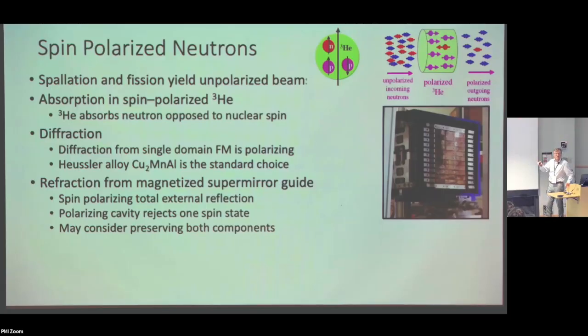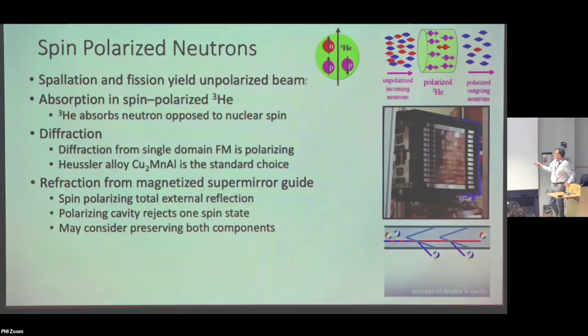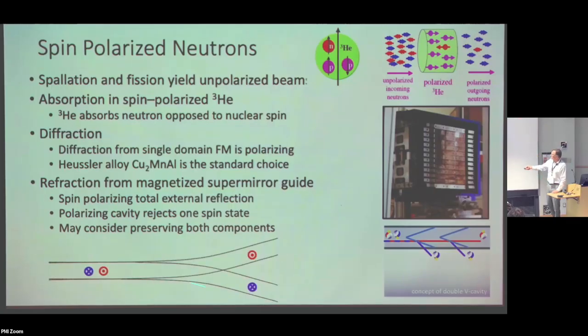Then there's polarized diffraction, where you use a ferromagnetic material and you use the nuclear magnetic interference effect to eliminate one spin state, and the other spin state will be diffracted. So that also loses you half of the neutrons, because the half that didn't diffract just passed through the monochromator. But we use that sometimes. You can also use a supermirror polarizer, which is a magnetic thin film that has a different index of refraction for the two different spin states. And so one of the spin states will be guided through the system, and the other spin state will be lost again. Again, you lose half of it. We've also been thinking about using a system where you just split the two beams apart and use both of them.